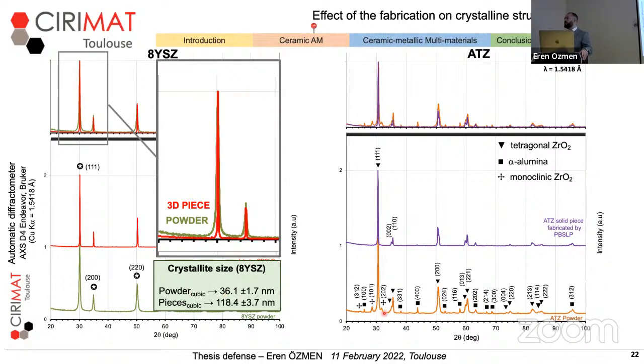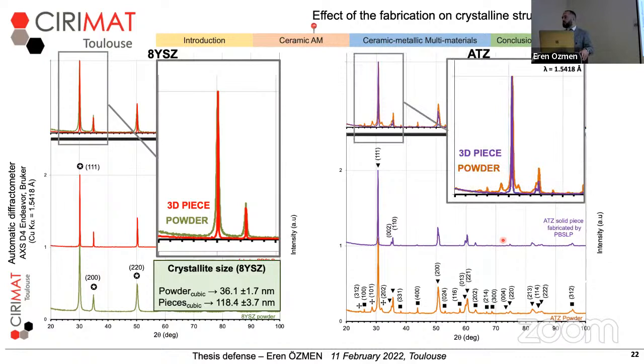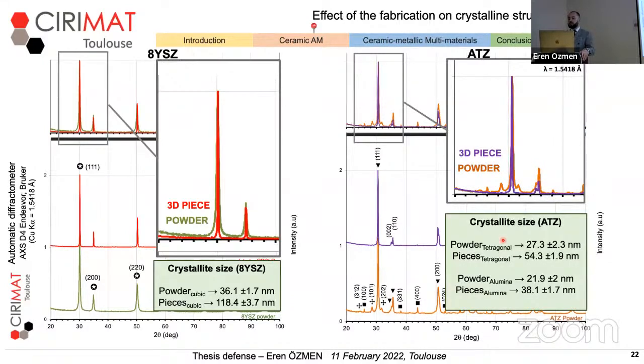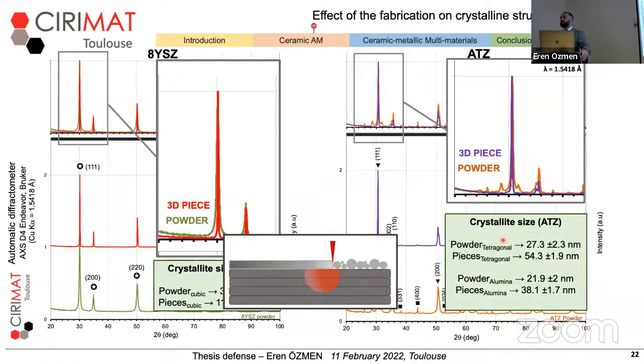When we check the ATZ before and after fabrication, the most significant change is the disappearing of the monoclinic phase, which appears in the powder and which we cannot observe in the solid piece. The solid piece was completely tetragonal phase zirconia. The same narrowing of the peaks was observed for ATZ as well. And when we calculated the crystallite size, we see crystallite growth also for the tetragonal phase and alumina inside the ATZ. The reason for this crystallite growth is most likely the melting, or, while upper layers are processing, the heat affected zone causing repeated heating in the lower layers, and that causes growth of the crystals.